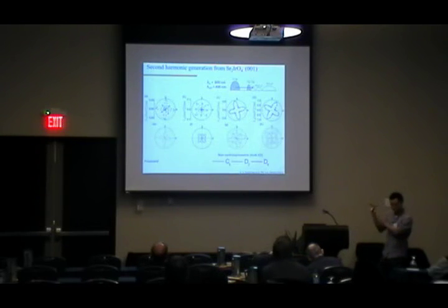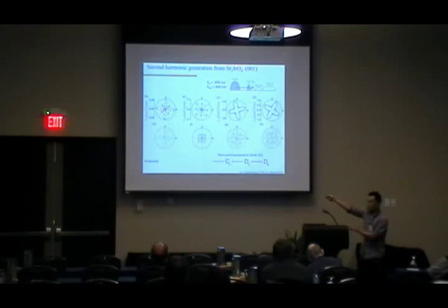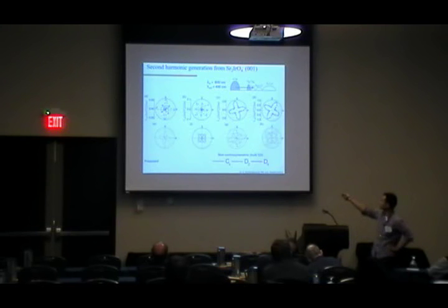Let me show you the way we do structural refinement. This is data: four rotational anisotropy second harmonic generation patterns taken from the 001 surface of Sr2IrO4 with an energy tuned to the charge transfer resonance in this material. These four patterns are the four different polarization geometries.